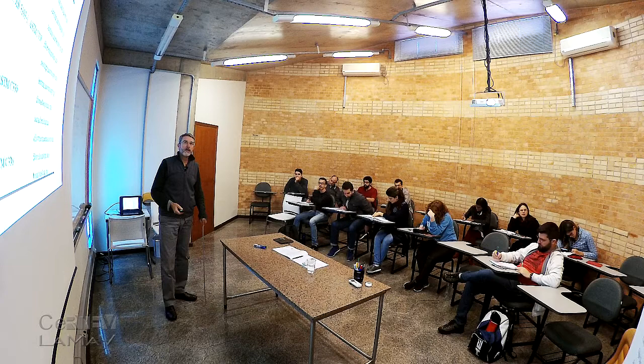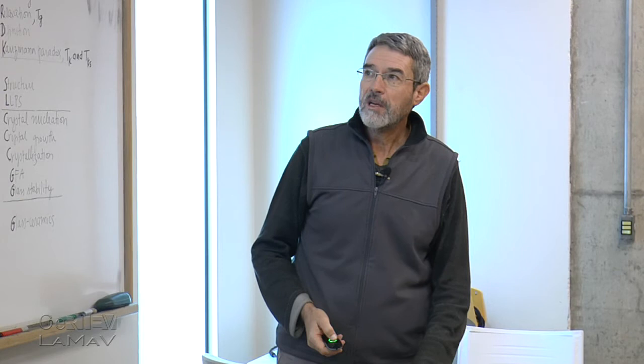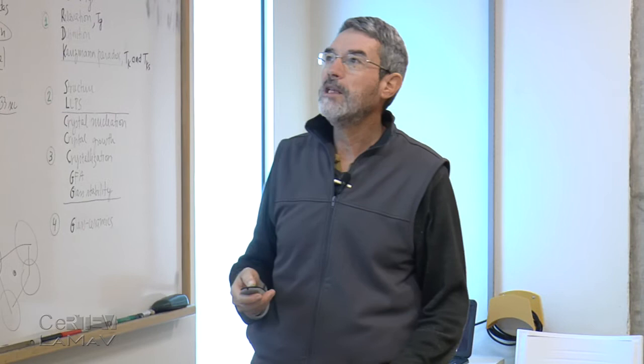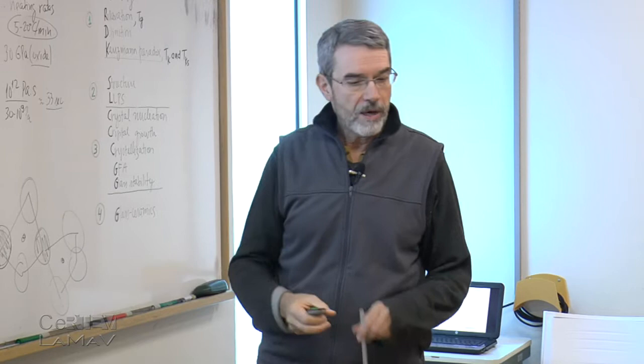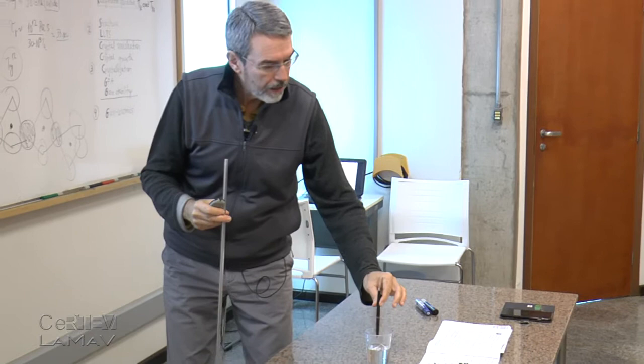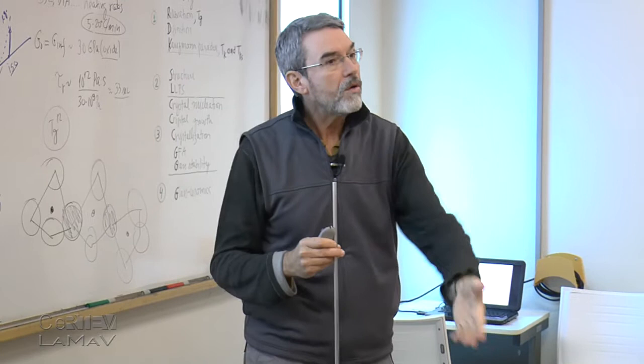Okay, I'm going to go very quickly to this table. People have invented many ways to estimate the viscosity of liquids. For instance, sometimes, like for you, Graziella, and you, Giannini, if you are interested in only measuring the viscosity at the liquidus, you can use some methods. You can, for instance, put a sphere in the liquid and measure the time it takes to sink down. If you know the geometry of the sphere and so on, you can calculate the viscosity of the liquid. Simple methods.